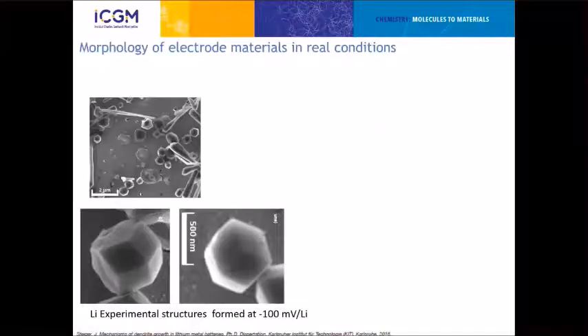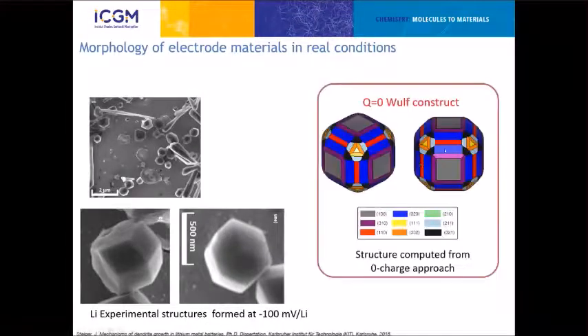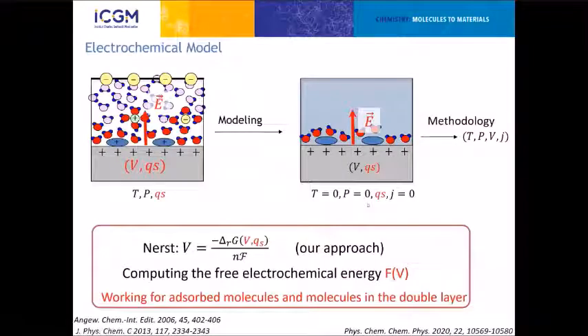As an example, I'm going to talk about the simplest system, the lithium reduction and formation of nanocrystallites. As you see, the shape of the nanocrystallites, if you compare it to what you get if you only use the surface energy from DFT calculations, is a very, very different structure. So the classical approach using zero charge can be very wrong in getting proper energetics for the interfaces.